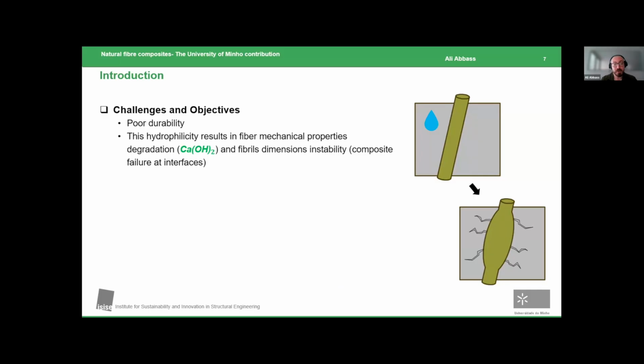It's rich with pore water, super alkaline, rich with calcium hydroxide. And these fibers, in turn, are composed of polysaccharides. They have a super dense network of hydroxyl groups, which yields these fibers' superhydrophilicity. So the moment they are in contact with water, they tend to swell, just to absorb this water.